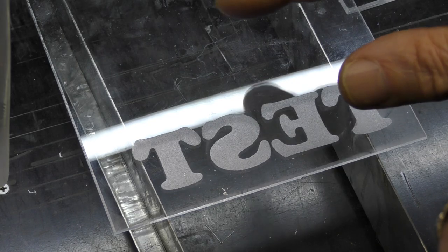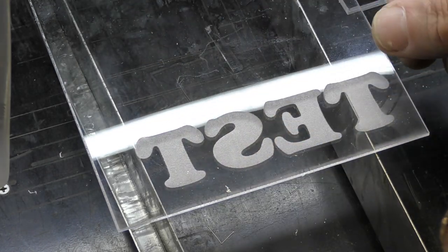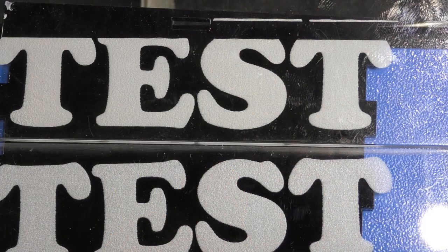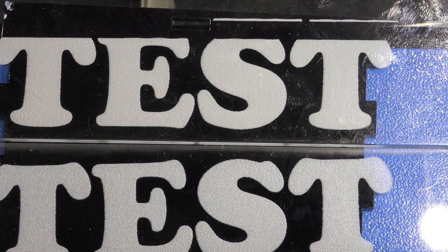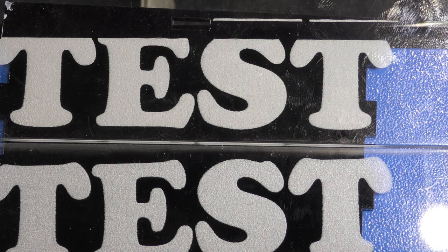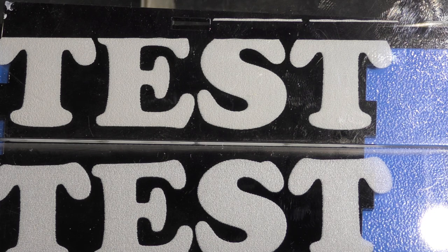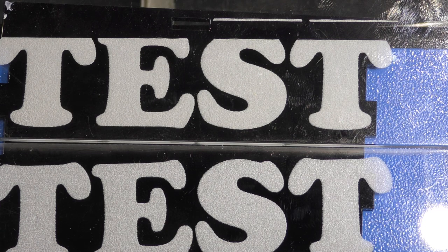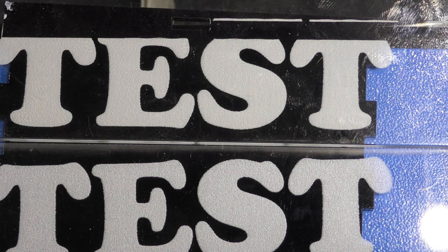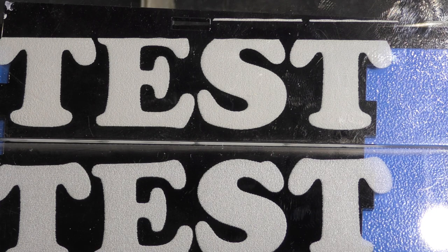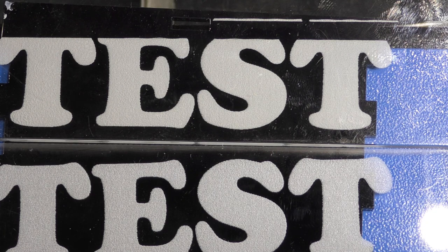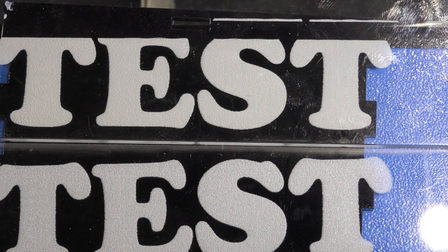We'll just clean this off to make sure that there's no white dust in here which is going to contaminate my visual assessment. So there is extruded and cast results against each other. Which one do you think is cast and which one do you think is extruded? There isn't a great deal to choose from them is it? But all I've done is change the parameters so that I've got more intensity into the surface. The point I'm making here is if you use the same parameters for testing both materials you'll get rubbish results. These are two different materials that you have to treat differently. And I think that test there proves beyond any doubt that if we like to play with the parameters we can get the same results as we did for cast acrylic. So I will tell you that this one at the bottom here is in fact the extruded acrylic.